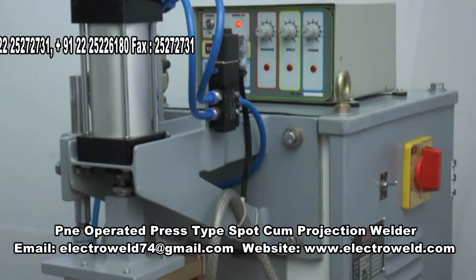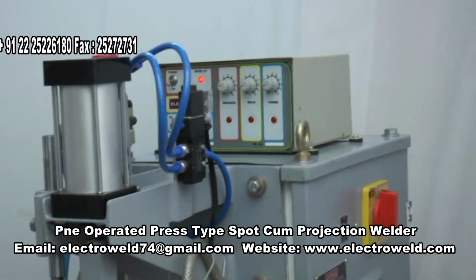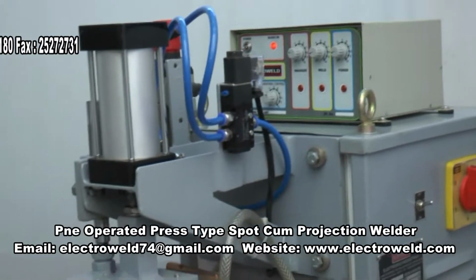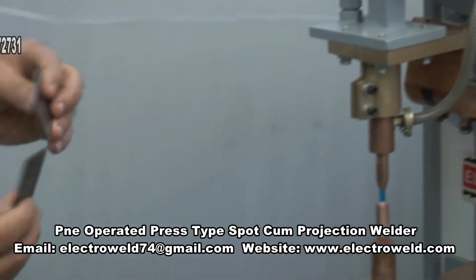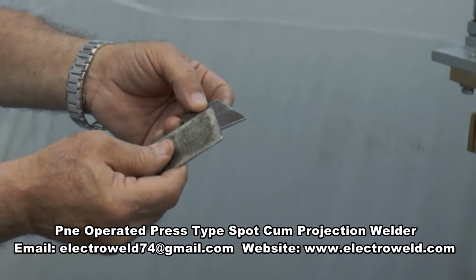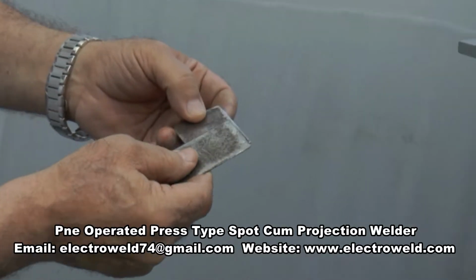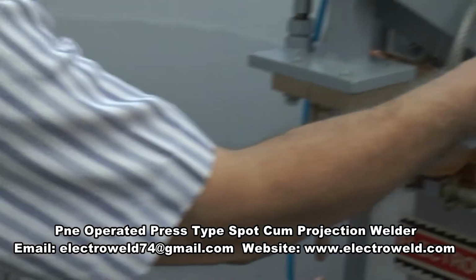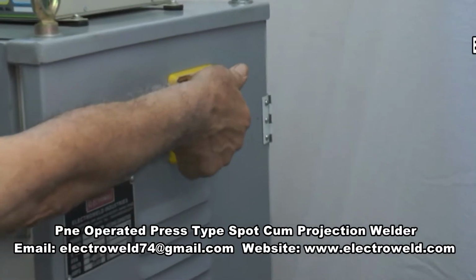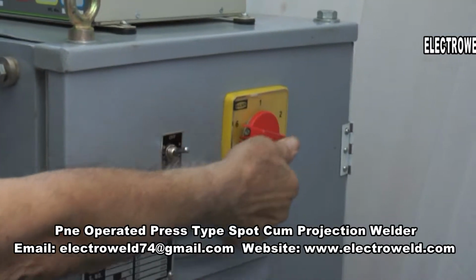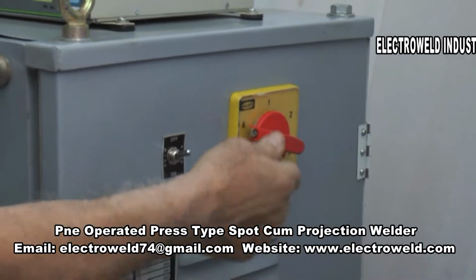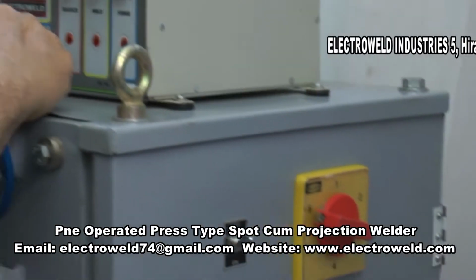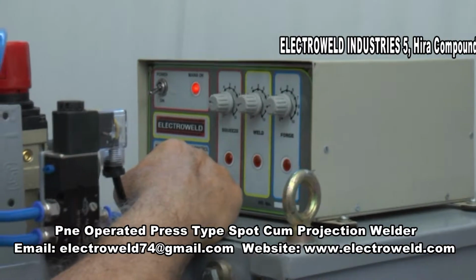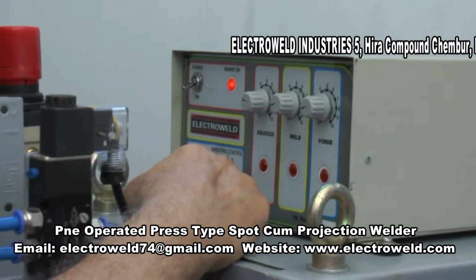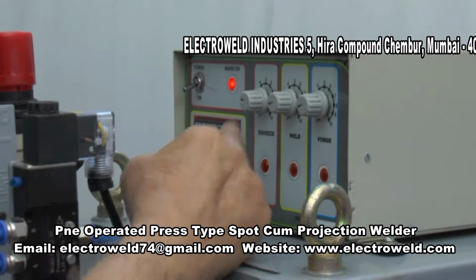Now we will show you the working. Supposing we wish to weld 2 mm plus 2 mm thick MS components. For this you have to adjust the current over here. So keep at number 3, and then the fine current over here you can set say number 5, say 50% of the particular tap.